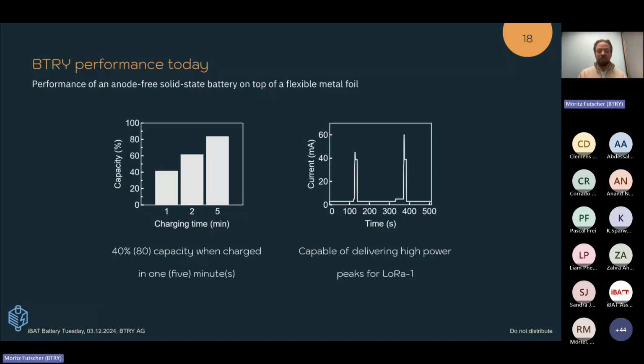We also showed the fast charging characteristics of our batteries on the left. You see what happens if we charge these batteries in just 1 minute. So what we do here effectively is we apply a constant voltage and to charge the battery for 1 minute. And if we do this, we get 40% of the capacity out again. So we can charge 40% of the battery, full depth of discharge in just 1 minute. And if we go to 5 minutes, we're already above 80% of full charge of this battery. And we know exactly where to work on to improve this even further.